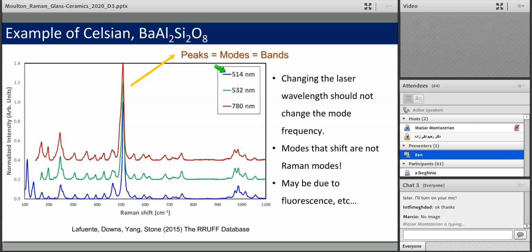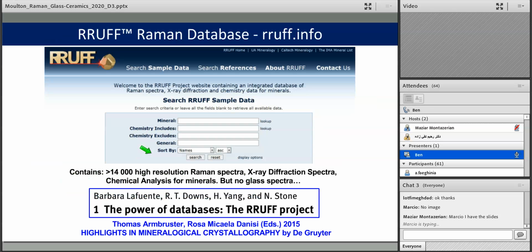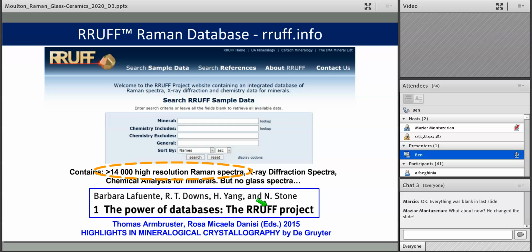Now, at this point, you might be saying, oh my goodness, look at all these peaks. It's hard for me to make sense of this. There is so much going on. So how do I determine what vibrational modes are in a given phase? And luckily for you, Barbara Lafuente and Bob Downs at Arizona State have created an open, free database called the RRUFF database, and it has 14,000 high-resolution Raman spectra of various crystals, from phosphates to carbonates to silicates and much more. They also have diffraction data and chemical analysis associated with these mineral phases. In their RRUFF project, they have developed software so that if you take a spectrum of an unknown sample, you can search through this database and it will tell you what the highly probable phases in your ceramic are.